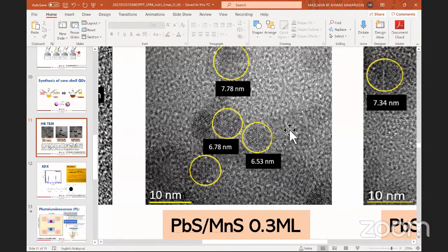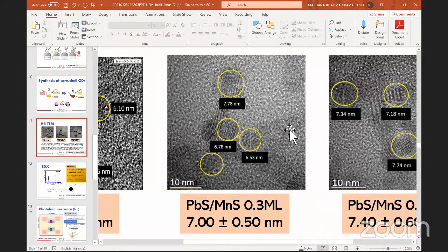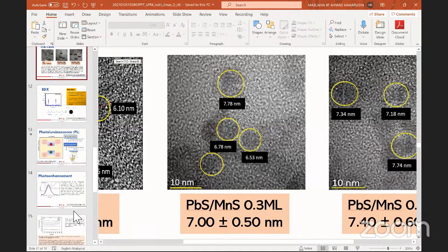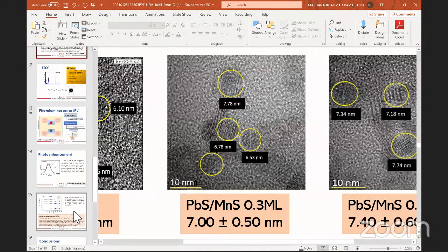Then you are claiming the shell size is this much, and all. But again, according to the TEM images, it shouldn't be. Please take a point on how you can claim core shell, and on what basis you are going to analyze the shell thickness. And one more thing you told: the PL data, based on that, the energy gap you find out. But I hope that is not sufficient, since you already claim it is a core shell. You can go for DRS or UV-visible, so it will give a better band gap value for your core shell structure.